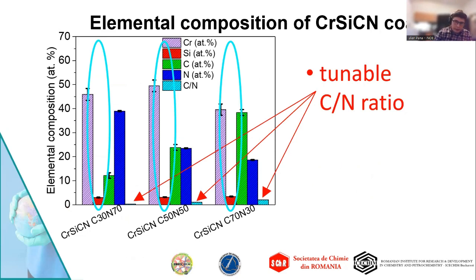The SEM analysis of our coatings showed what we intended: the carbon content is increasing for all of our coatings, represented here by the green color, while the nitrogen is decreasing among our substrates. That proves that we have a tunable carbon to nitrogen ratio, which increases as we change the reactive gas flows during the deposition. Also, we see here in red that silicon is present in the coatings.